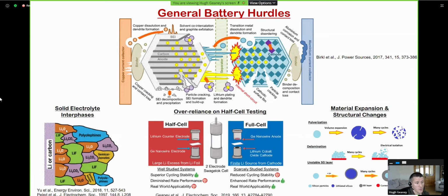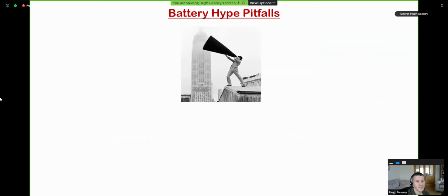Also, you can imagine the SEI on the surface is usually a very thin layer. If you have lots of volume expansion and contraction, you're constantly changing the surface of the material, and this SEI can break and have to reform. One of the key issues with the SEI, particularly for the alloying materials, is it consumes lithium. If you're working within a full cell, you can actually deplete your lithium inventory for your entire battery. So you can have enhanced capacity fade compared to a half cell.